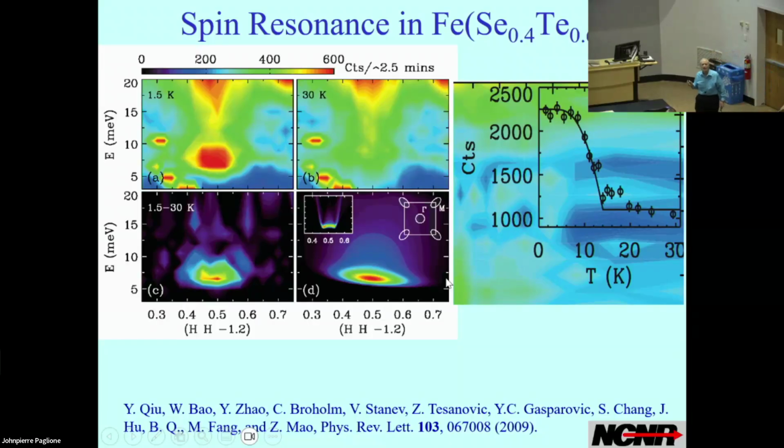Yep. How do you know if the excitation is from S± pairs? Oh, well, that's a good question. Just looking at it, you don't know. But you do know that there has to be a sign change of the pairing on the Fermi surface, whether it's plus minus or D wave, which is going around 90 degrees. This data won't show it. What you need to look at is, first of all, you need to know where this occurs in reciprocal space. It only occurs at one place. That can be a hint, but it doesn't prove it.